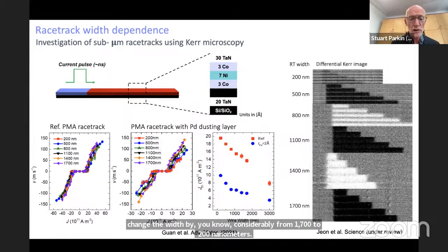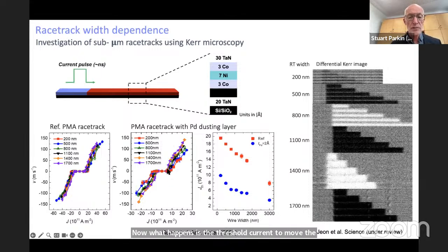Now, what happens is the threshold current to move the domain walls, which you can see is about 5 times 10 to the 11 amps per square meter, does increase a little bit as we reduce the width, but not much. So this was quite a surprise to us that the threshold current to move the domain walls, which is really determined by inhomogeneities within the layers themselves, would be so little affected by this dramatic reduction in the width of the domain walls. So this is as far as we can go optically.